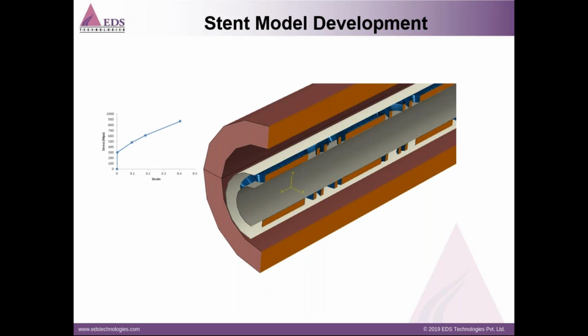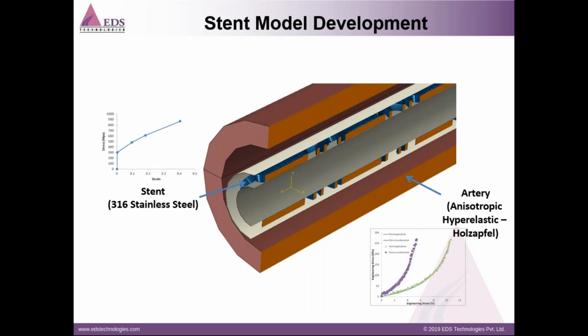The artery is modeled as a solid cylinder, and when it comes to material property, we have defined it as an anisotropic hyperelastic Holzapfel material. So basically, the artery is modeled as a Holzapfel material using an anisotropic hyperelastic material model. You can see the bottom graph showing the stress-strain curve, and also the material property that is used, and it matches very well with the experimental data. This is the experimental data we had for this particular artery material.